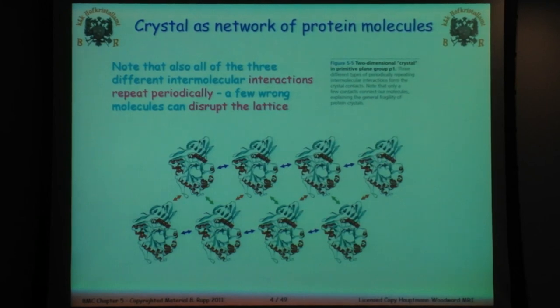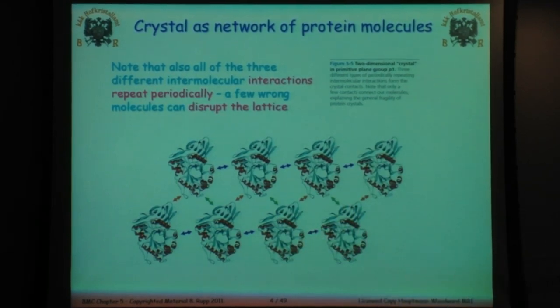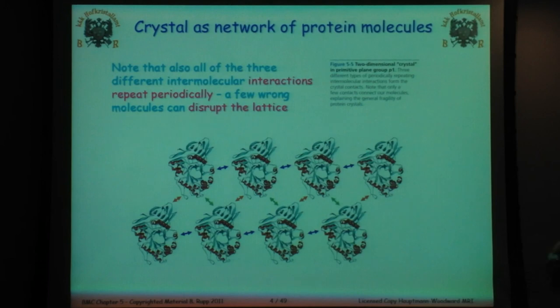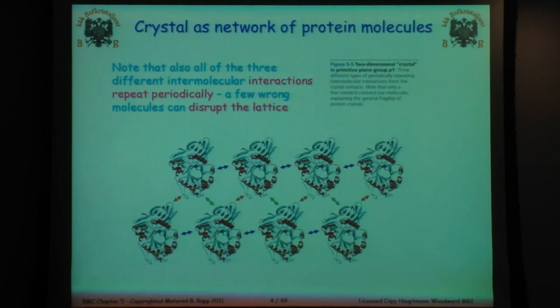When you're crystallizing something, all you're really trying to do is effect about 10 intermolecular interactions. You'll see the same interaction between each protein. If you had an imperfection, another kind of protein, or some kind of mutation, that may not happen and then you may not get your crystal. That's why when you get a protein crystal and put a pin on it, it will crush and go to mush — it's not held together very strongly. This is also a destructive test: if you crush the crystal and it goes to mush, it was protein; if it clicks, it was salt.